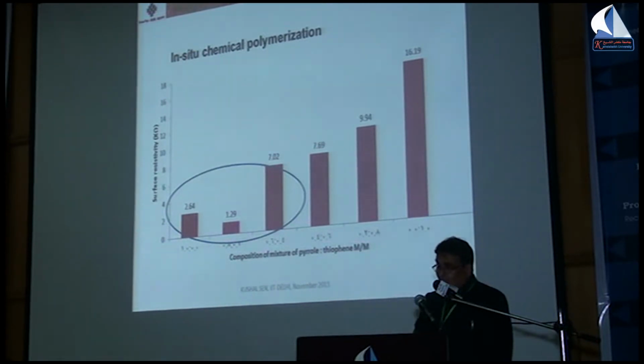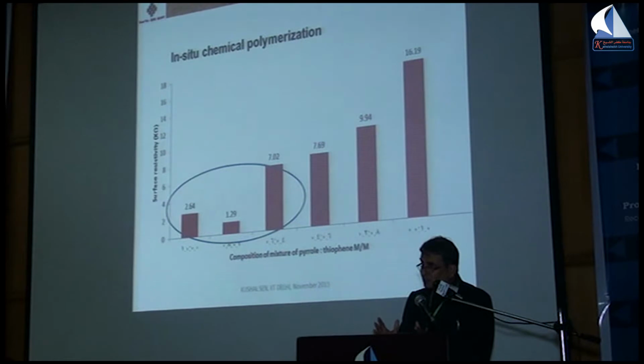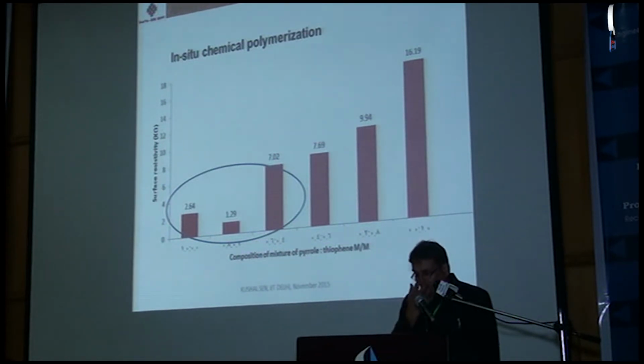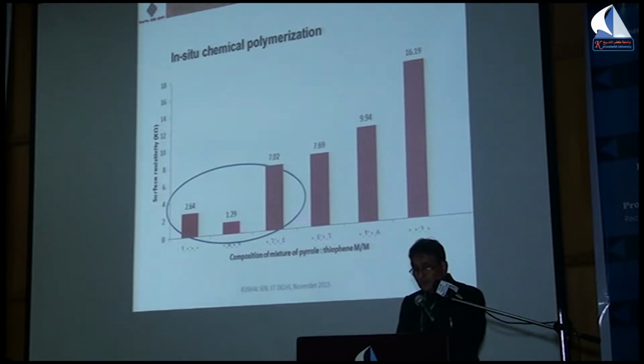What is happening is, from one side to the other side, the ratio of the two monomers has been changed. One side is 100% pyrrole, on the other side it is 100% thiophene. Those type of things. And we saw that the resistivity increases. It's quite conducting material, by the way. When you have a 4 kilo ohms kind of environment, it's quite conducting. But one can make it more conducting also.